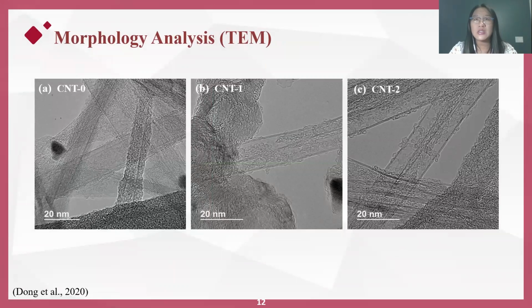The internal structure of as-produced CNTs was reviewed with high-resolution TEM in this slide. For the control group, the predominant component observed was multi-wall CNTs with a diameter measured from 19 to 23 nanometers. And double-wall CNTs start to emerge in the CNT1 group, accompanied by some multi-wall CNTs with more than 10 walls on the side. With an even higher water concentration, the CNT2 group demonstrated a great majority of double-wall CNTs with diameters ranging from 10 to 15 nanometers. These findings were in good agreement with the TGA analysis, where the derivative peak shifted to lower temperature that we have mentioned earlier.